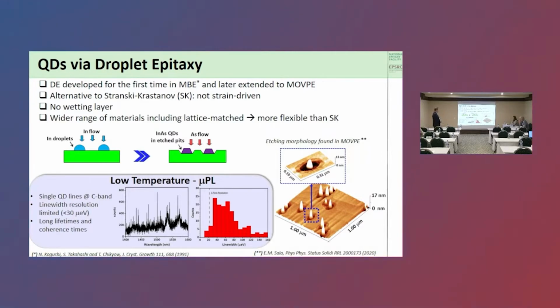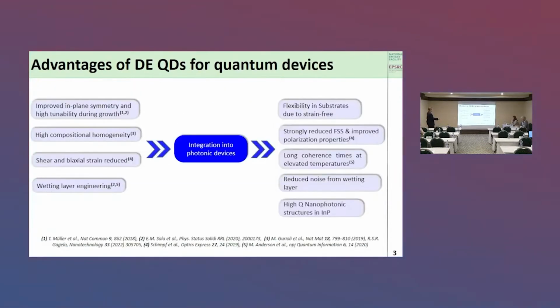The line widths that we have typically in this industrially compatible MOVPE reactor are typically around 60 micro eV, but we do have a part of this distribution that is below the resolution limit of our spectrometer, which is around 20 micro eV. So these dots are good quality and have good coherence properties. One thing that we found in the MOVPE growth is that these dots form within an etched pit around the dot, and that's interesting, but also potentially important in terms of the site control, which I will come on to.